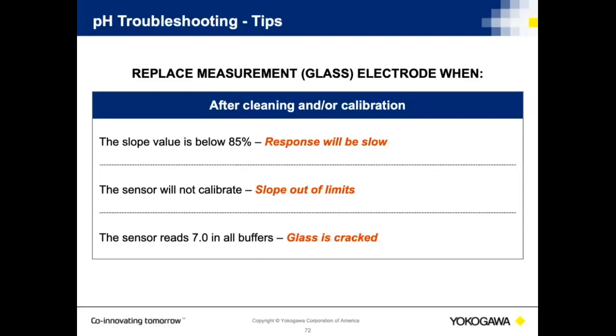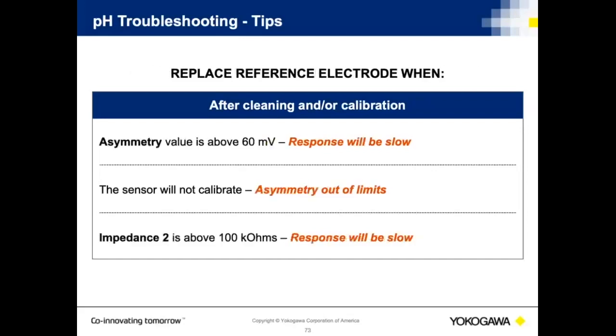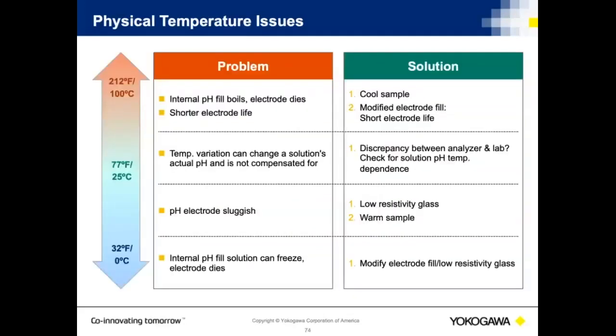The slope is out of limits. The sensor reads 7 pH in all buffers. Probe is probably cracked. Reference electrode, asymmetry values above plus or minus 60 millivolts. Response again will be slow. Asymmetry out of limits, or the resistance values are above 100 kiloohms, which is quite a high resistance for a reference electrode. What do? You replace it.